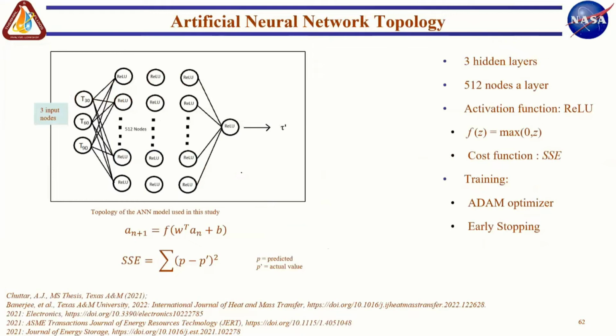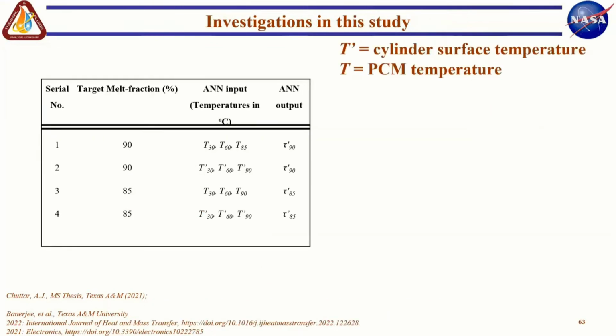We had 3 inputs, the 3 temperatures measured by the thermocouples, either on the surface or within the PCM at 30%, 60%, and 90% melt fraction locations. And we did the training with the experimental data. We set aside another set of experimental data for the validation and checking the error in our prediction. So we had 2 sets of prediction, one based on the surface temperature, and then one based on the PCM temperature.